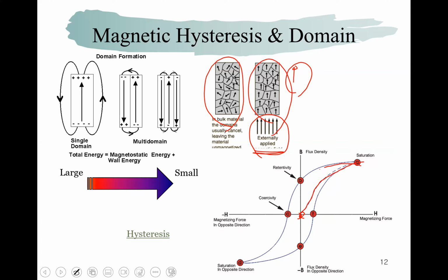And when we reduce the magnetic field, they form the multi-domain, and this value is less than the saturation value. For the negative field, they start to reverse some domains. And finally, at a certain field, which we call the coercivity, the average value of the magnetic moment is zero again. But we need a certain amount of negative field instead of zero field. And if you apply an even stronger negative field, they align against the original direction, and so on. So this is the hysteresis rule.